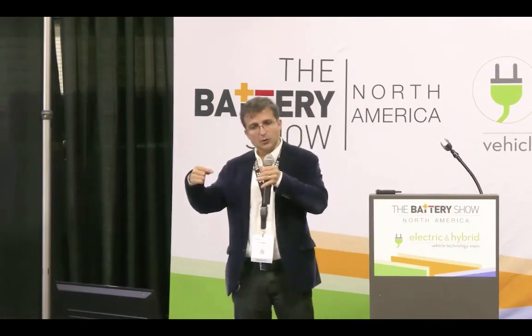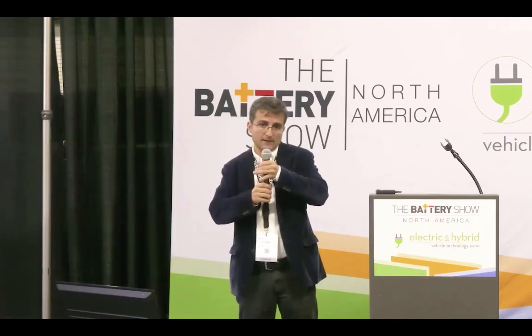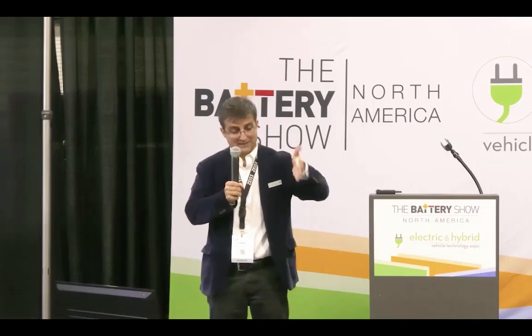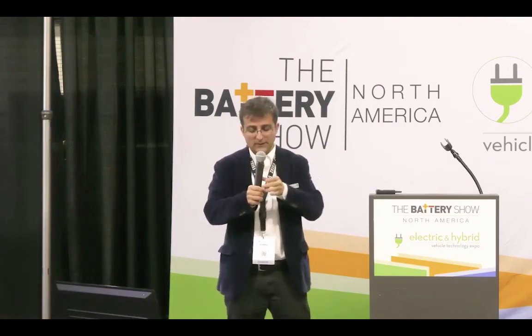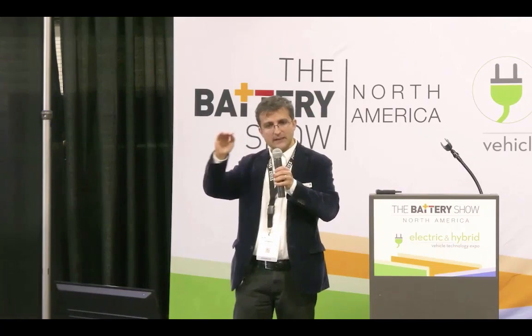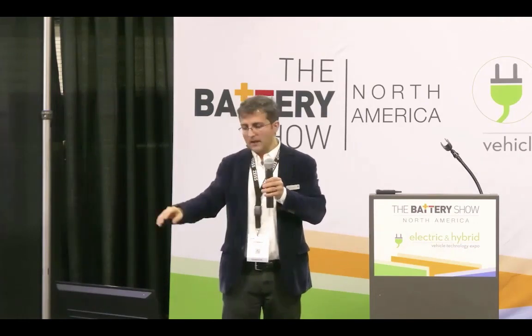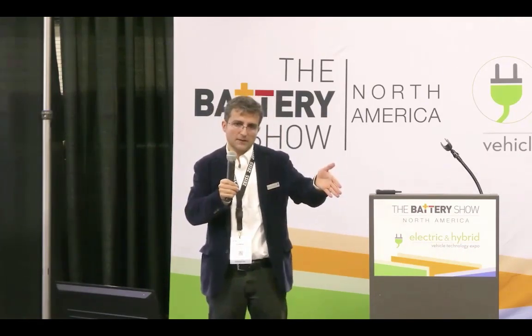Yeah, so let me explain a little bit of how the physics of X-rays work so we can understand the size limitation. When you shoot X-rays through a sample, the X-rays penetrate the sample and pass across, and then you have a detector. What the detector sees on the other side is the transmission of the initial signal. There is an attenuation of the signal. It is an exponential attenuation, which means that what you see on the other side is going to decay. There are two terms that drive that exponential curve. One is the thickness of the sample, and the second one is the density of the sample. So if you have very high atomic number elements, then the penetration is shorter. And if you have thicker samples, then the signal that you see on the other side is less.